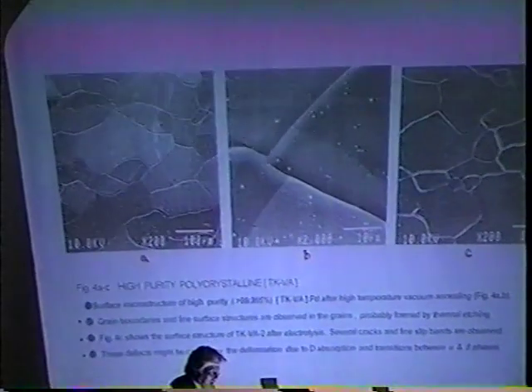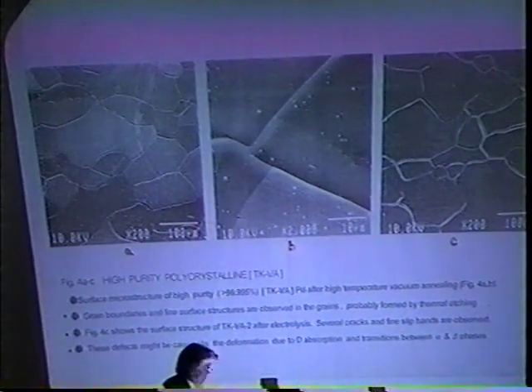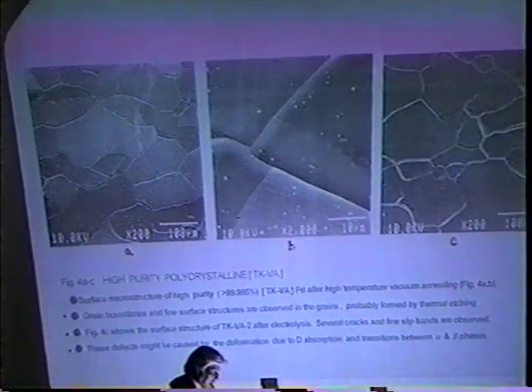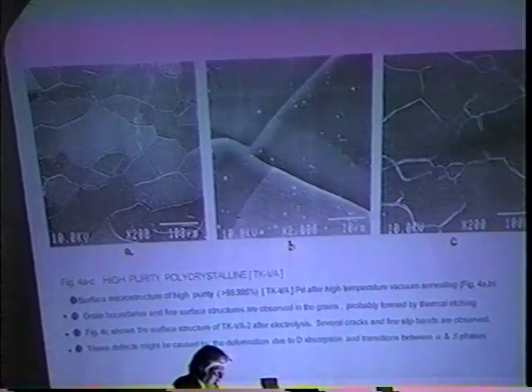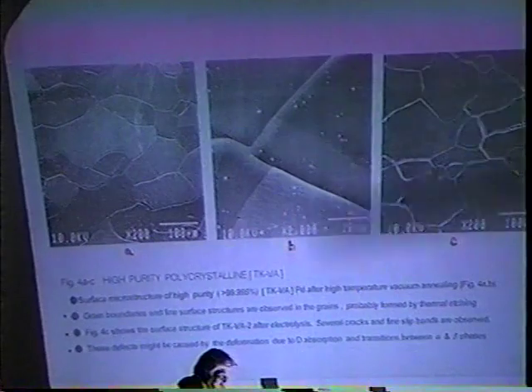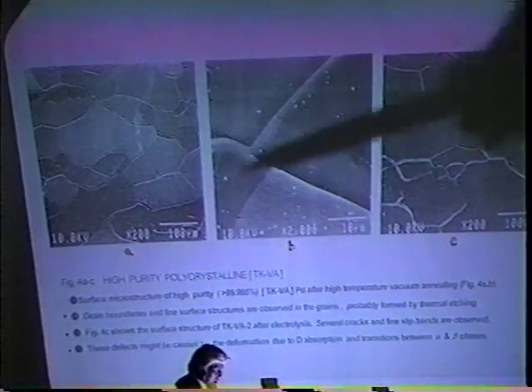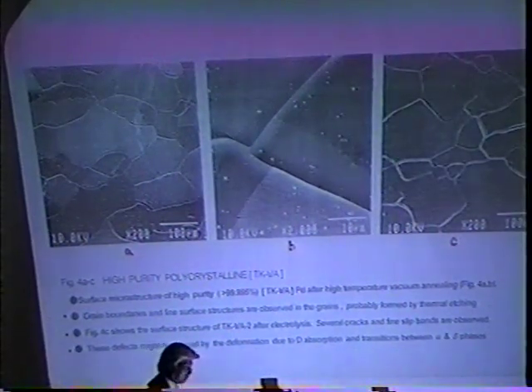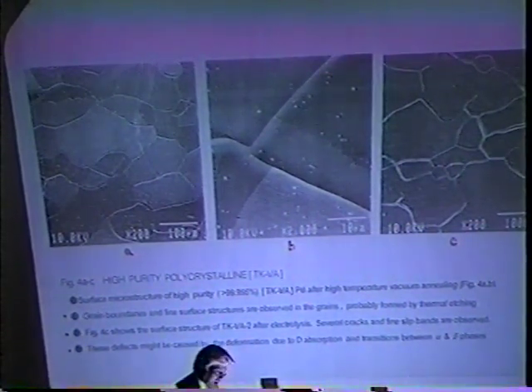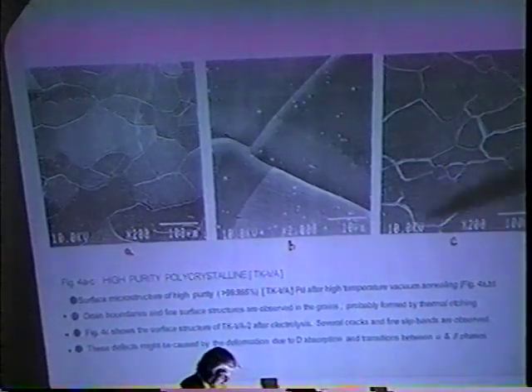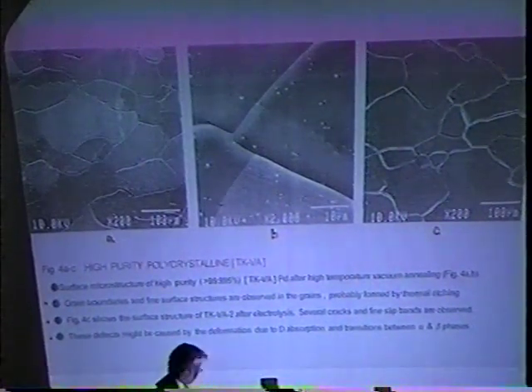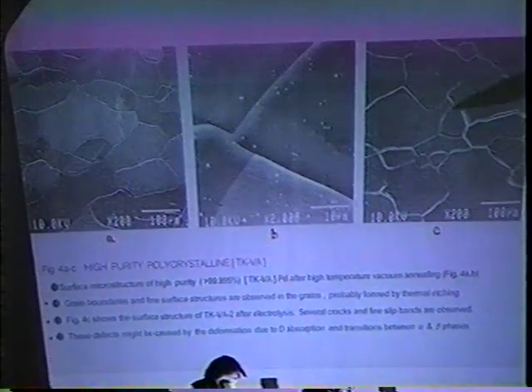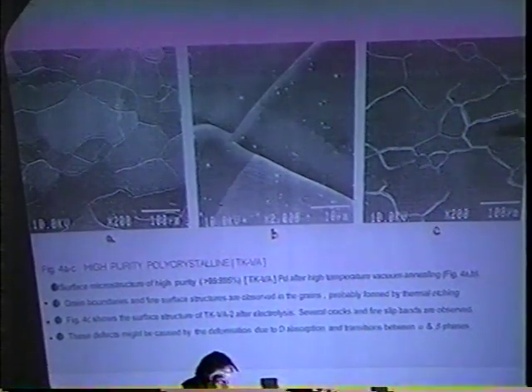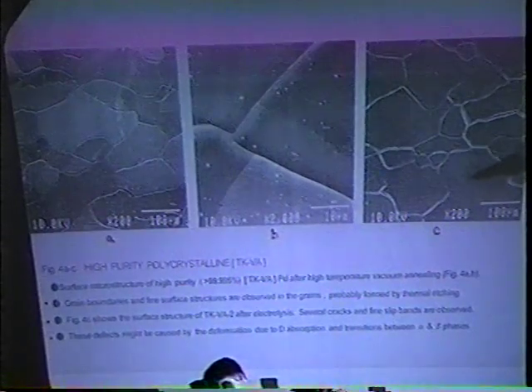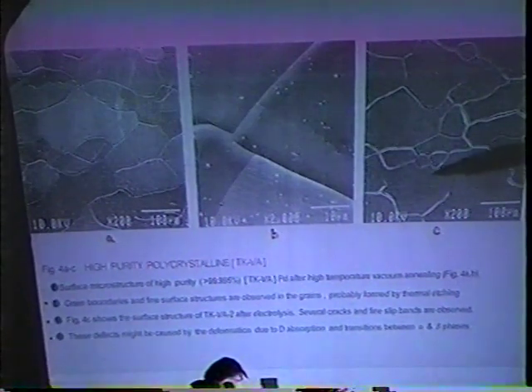In the high purity materials, greater than 99.995% purity, the before-electrolysis samples, you can see the grain boundaries and very fine structures. These fine structures and grain boundaries may be made by thermal etching at a high temperature and high vacuum state. In the case of after electrolysis, you can see the microcracks along the grain boundaries, and also observe the fine slip band like a single crystal.